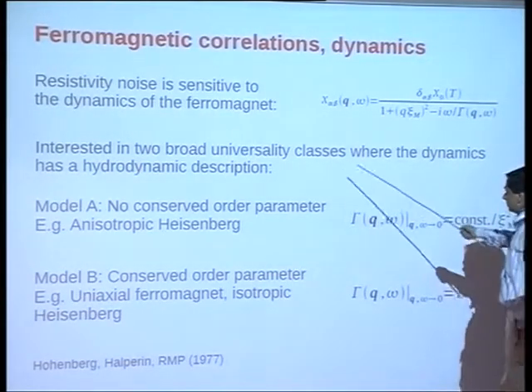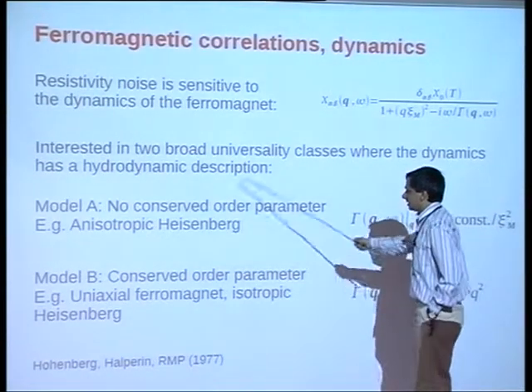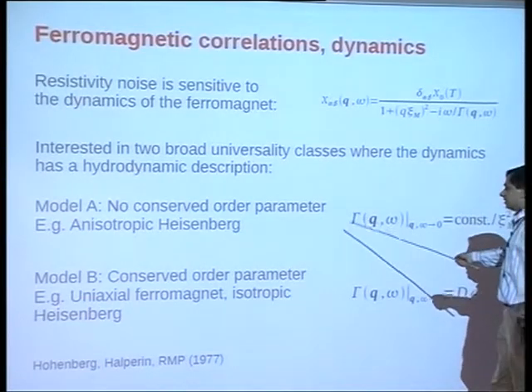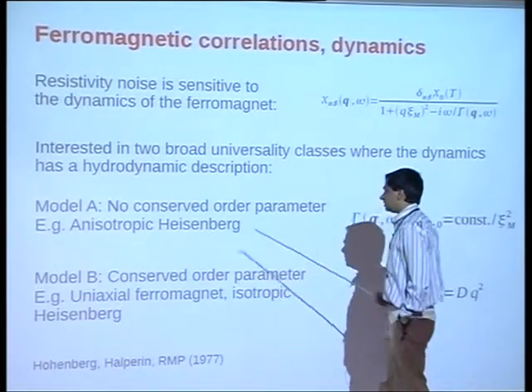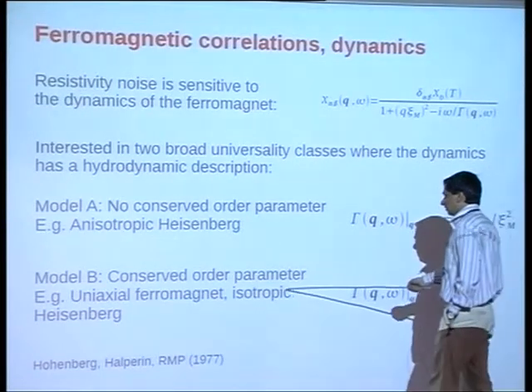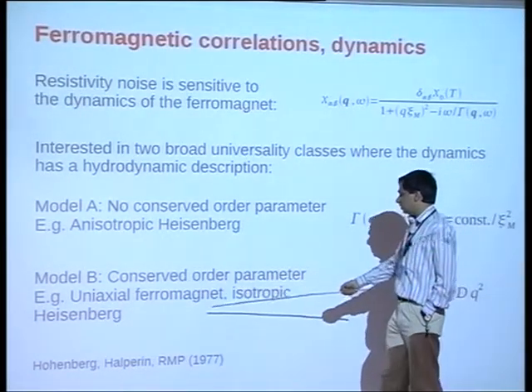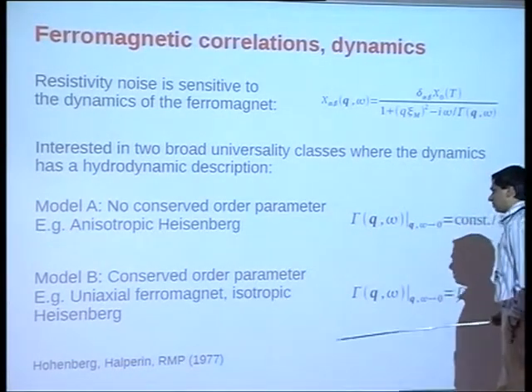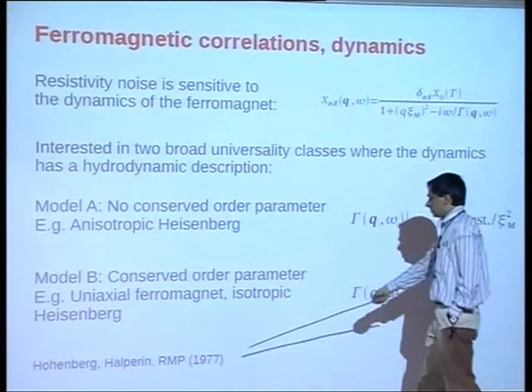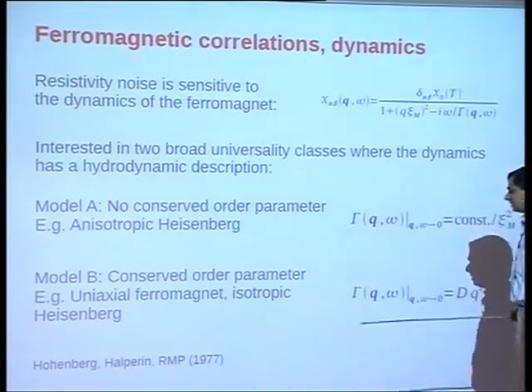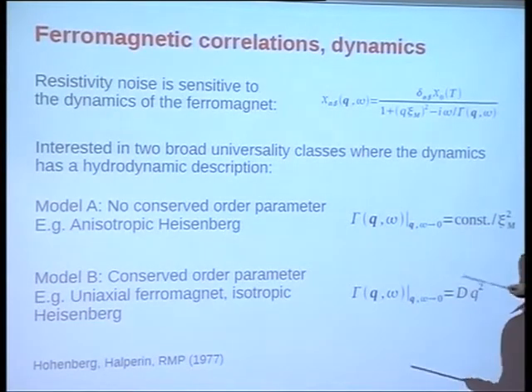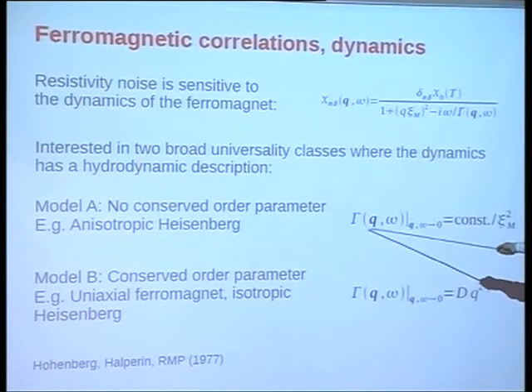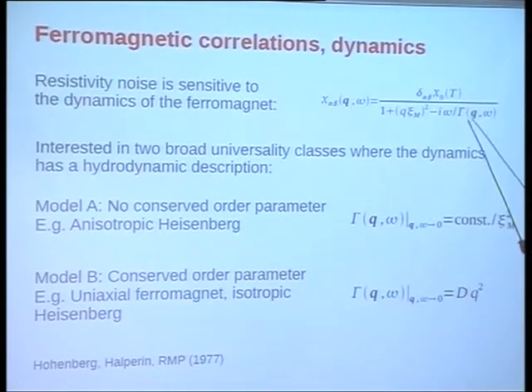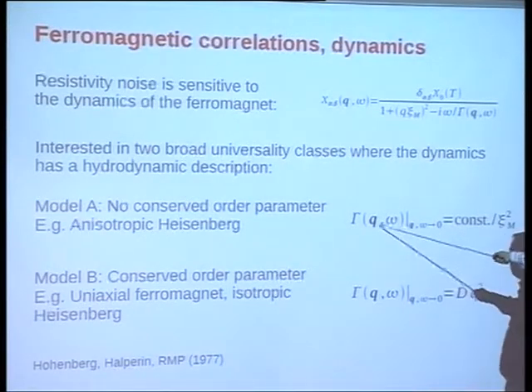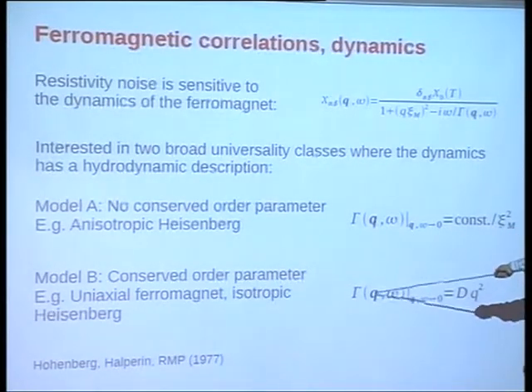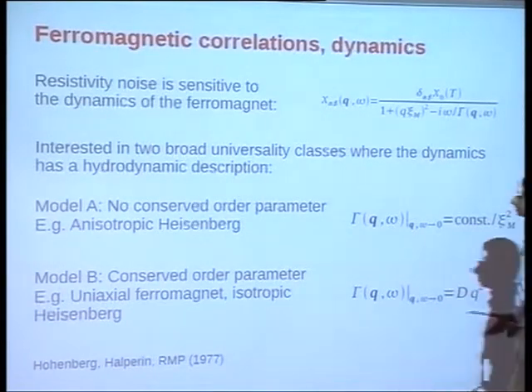Well, I'll be showing you two different classes. One is where there is no conserved order parameter, such as the Ising or anisotropic Heisenberg model. And then there's another one where the order parameter is conserved, such as a uniaxial ferromagnet or an isotropic Heisenberg ferromagnet. These classes are the same as those discussed in this monumental review by Hohenberg and Halperin. In the case of model A, the damping of the dynamical spin susceptibility is independent of q and omega at small q and omega. And for conserved spin dynamics, it goes like the square of the wave vector.